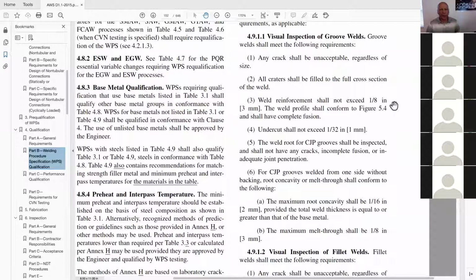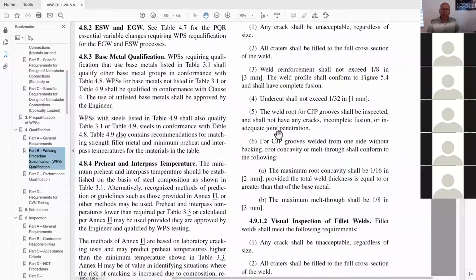If they can detect that themselves, if they're trained to inspect their own welds and they see that their cap pass exceeds 1/8 inch, they can remove it and re-weld it while in process. But the finished product cannot be modified to not exceed 1/8 inch by grinding, because then he did not demonstrate the skills of welding. Undercut is allowed, but no deeper than 1/32. And here's the deal that I'm trying to get to. Item number 5 in the visual inspection of the weld test coupon calls out for the weld root to be inspected for all CJP groove welds.